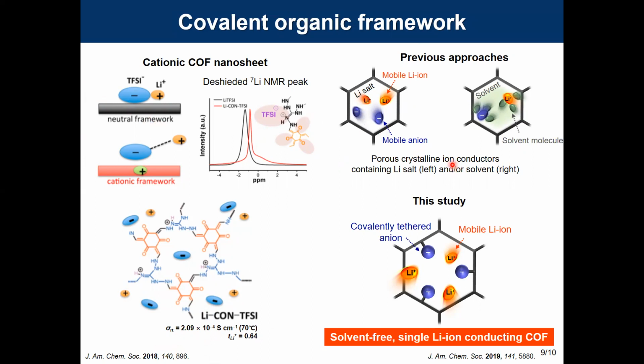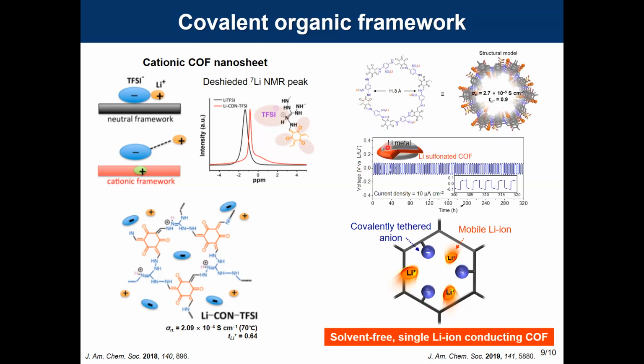Another COF is lithium sulfonated COF as a new class of solvent-free single lithium-ion conductor. So benefiting from well-designed directional ion channels, the high number density of lithium ions and covalent tethered anion groups, the COF exhibits an ion conductivity of 2.7 × 10⁻⁵ Siemens per centimeter with a high transference number of 0.9 at room temperature without any kind of sorbent salt and organic solvent.